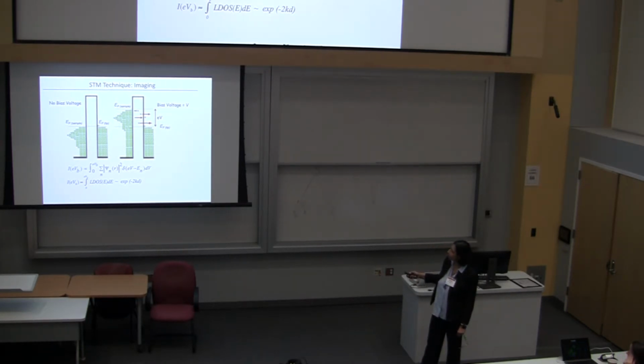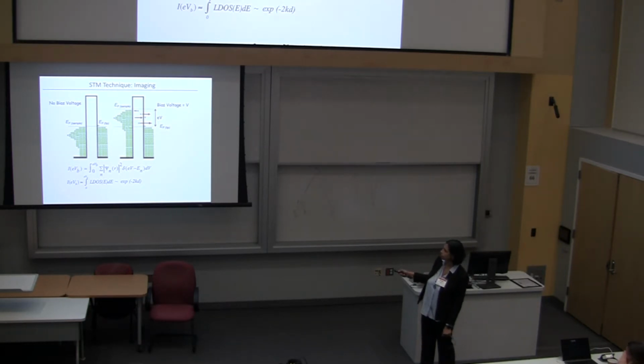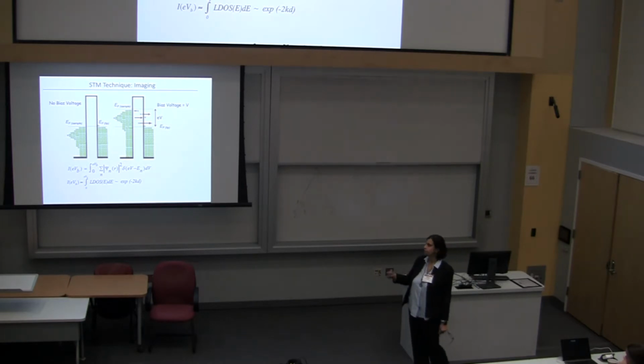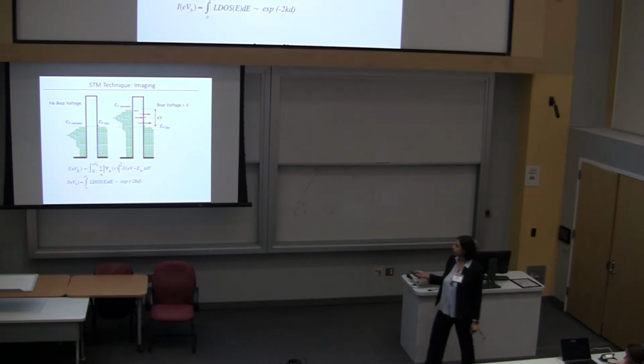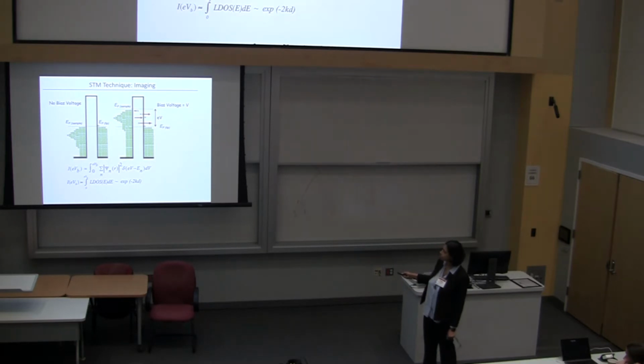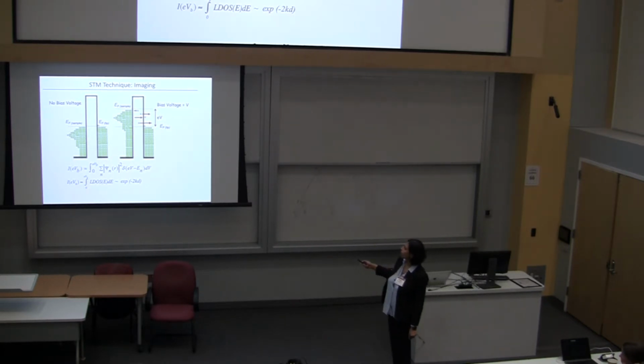So the tunnel current I is proportional to the integrated density of states. This delta function is just counting the states: how many states you have from 0, which is the Fermi energy, to the bias voltage, which is somewhere here. That's the delta function counting. But then notice one really important thing. Because of the way STM works, you need to have the wave functions actually overlap between the tip and the sample. Because of that, the tunnel current is proportional to the square of the wave function as well.